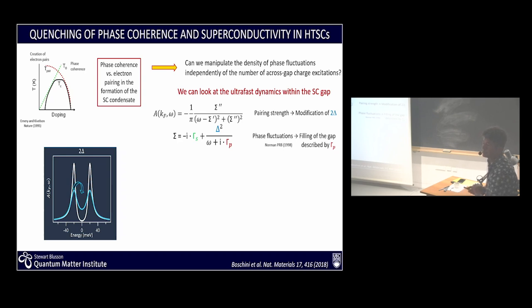Is one of them elastic and other inelastic? Well, I would say both of them can have an inelastic component. It's just one is really for the single particle, the other one is for the Cooper pairs. Right? So one single particle, Cooper pairs. And again, I like to link the gamma p, of course, to phase fluctuation. The point I want to make is that if you have phase fluctuation, of course, you're going to see an action in the gamma p. Now, if you see an action in the gamma p, I like to make the connection to phase fluctuations being important. So let me now go to the experiment, having in mind these two scenarios, the closing of a gap or the filling of a gap.